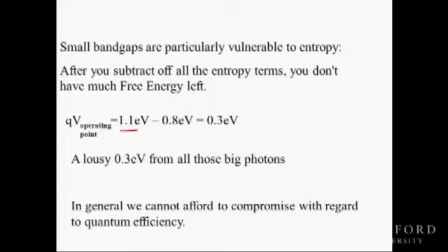If you start with 1.1 volts, which is the band gap of silicon, and now if you add up all the terms on the previous slide, you're losing 8/10 of a volt. So by the time you're at your operating point, you've only got 0.3 volts output. That's from all those big photons. You had 2-volt photons. You had 3-volt photons. And all you end up with is a lousy 0.3 volts. Now, if the band gap started smaller than 1.1 volts, then you could end up with nothing.